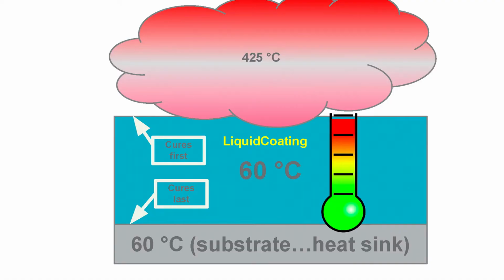So when you go into a coil line, what I'm showing here in this picture is you've got this huge piece of steel, which is a heat sink, and you're going into a really hot oven. And we've got a thin coating, but the thin coating is going to heat up because of this air, but the substrate's going to keep it cool. And what ends up happening is you end up with all kinds of issues, but primarily you're going to have problems with blistering if you don't get the chemistry right.